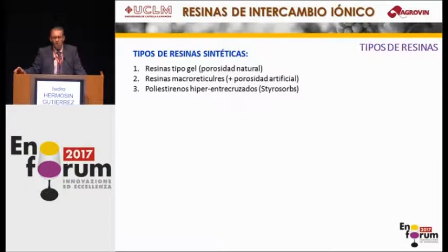In that case, you increase the percentage of cross-linked material, for instance, polystyrene, with a higher quantity of vinyl benzene, and you use a mixture during the formation of the copolymer, and it is a porogenous substance, that is, those substances that do not participate in the copolymerization reaction and that prevent the formation of polymers in the place they take, but then they can be easily removed.